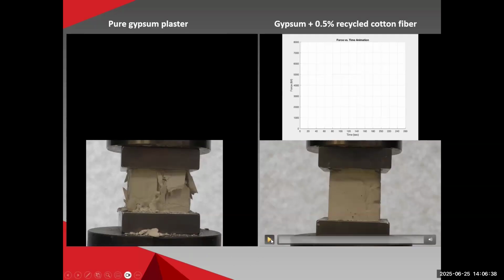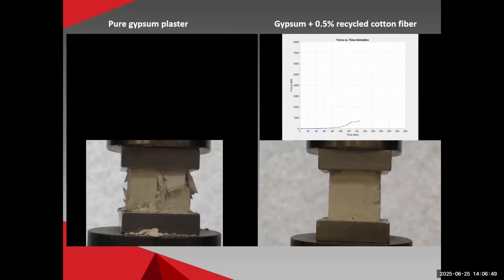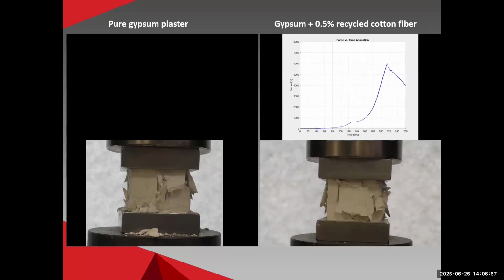And we stopped it after it just started falling apart, but you can also already see a large amount of material around the bottom. Then if we try the material that has 0.5% weight percent of cotton in it, you'll see a similar shape to the curve, but as it breaks, you'll see the material doesn't fall away. It stays more or less connected until, if we kept going, it would go a lot further. But you can't tell too much from the curve at the top, except for the fact that it's still supporting a significant amount of force. The amount of force it can hold, or the amount of weight it could hold, doesn't fall off as rapidly either. So hopefully that's an example that can demonstrate the value of having fibers in something as simple as a plaster.